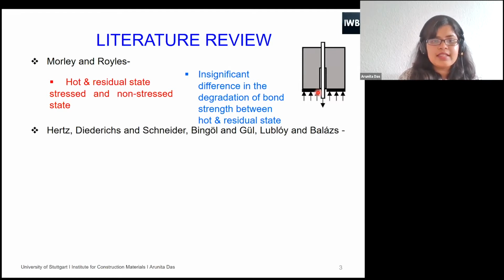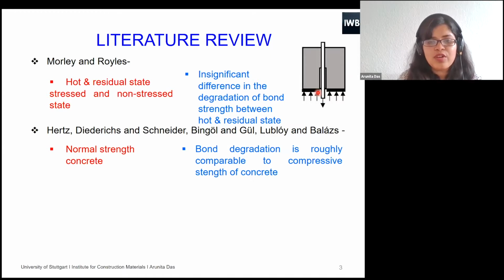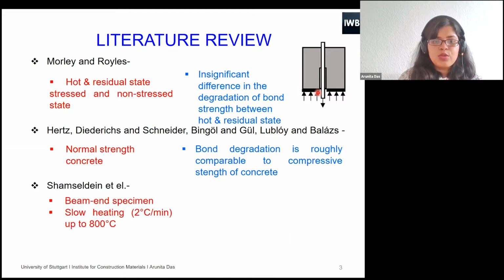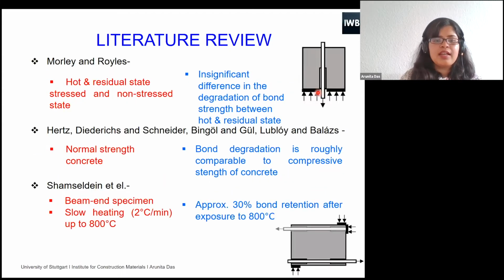Later on, Hertz, Diederichs and Schneider, Bingöl and Gül, Lublóy and Balázs all considered normal strength concrete, and they also concluded that the bond degradation is roughly comparable to the compressive strength of concrete. All of them considered pull-out specimens and confined test setups. Later, Shamseldein et al. were the first to introduce beam end test specimens in case of fire, but they considered a slow heating rate, which is 2 degrees per minute, and they concluded that approximately 30% of bond is retained after exposure to around 800 degrees Celsius.